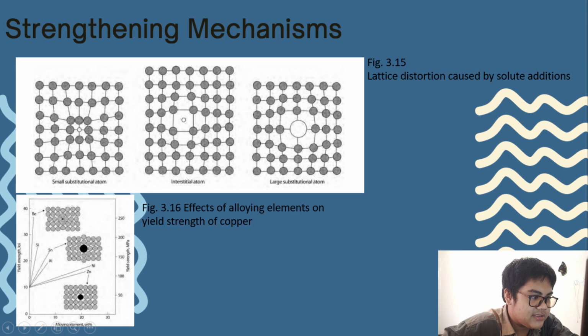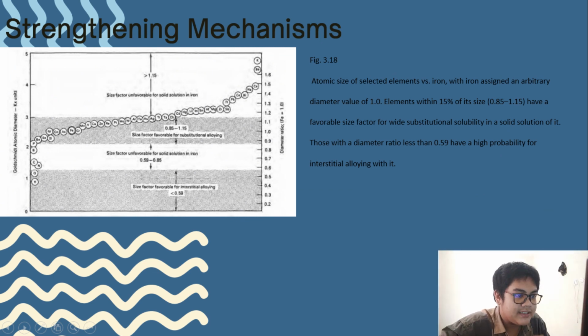And next we have figure 3.18, atomic size of selected elements versus iron, with iron assigned an arbitrary diameter value of 1.0. Elements within 15% of its size, from 0.85 to 1.15, have a favorable size factor for substitution and solubility in a solid solution of it. Those with a diameter ratio of less than 0.59 have a high probability for interstitial alloying with it.